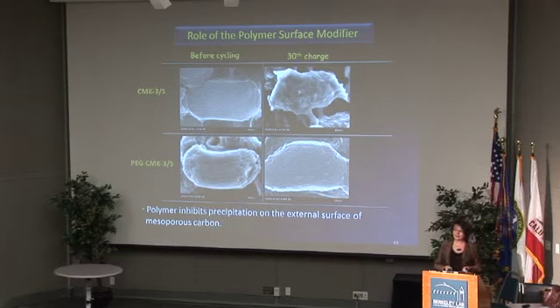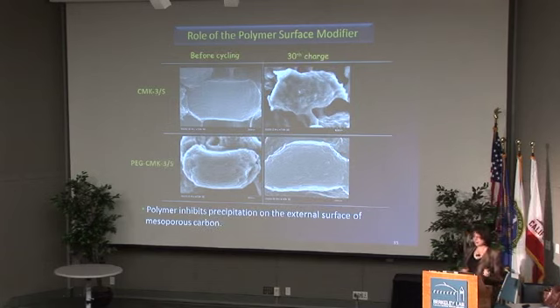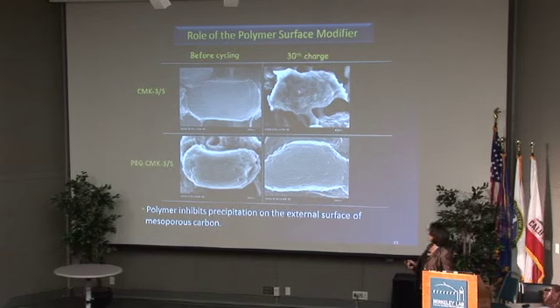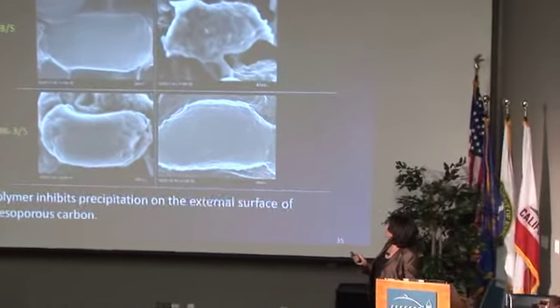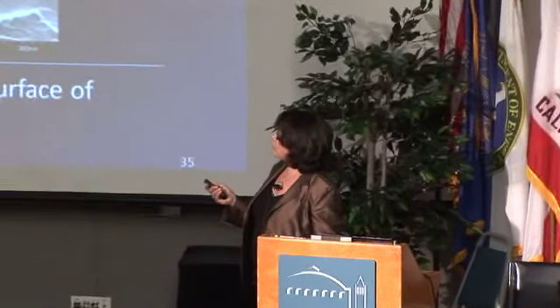The other important point is that that array of carbon wires, which are slightly porous, also are somewhat efficient for encapsulating the sulfur. They're not perfectly efficient. So this shows the surface of the electrodes before cycling and on the 30th charge for CMK3 sulfur. So this is just sulfur incorporated in the carbon. And you can see on the 30th charge that we do have an unpleasant looking coating on the surface, which are the soluble polysulfides, which have now reduced to form insoluble sulfides on the surface. The problem with that is that these are fairly impermeable to lithium-ion diffusion, and therefore they inhibit the reaction. But still, we're doing pretty well compared to some other systems.